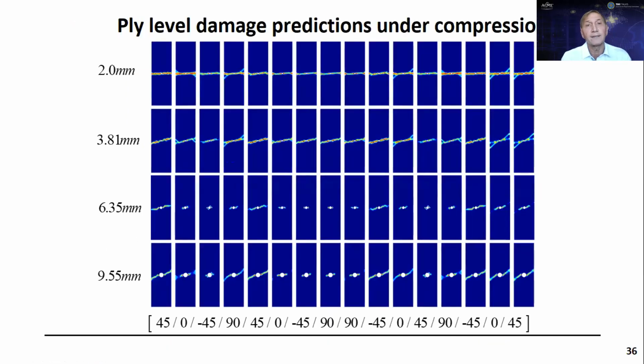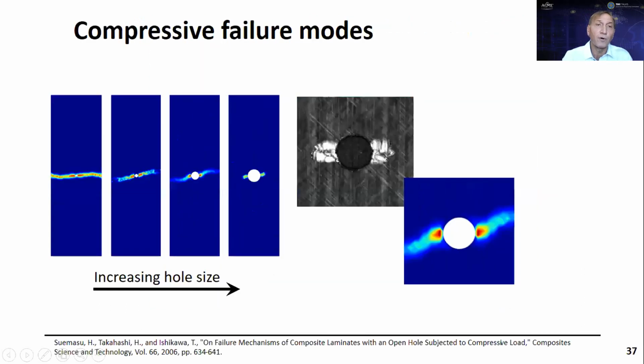And next we'll look at the same laminate, this time in compression. Now, if you remember, for the smaller hole size, we had these slanted failure paths, but now it's very straight, perpendicular to the direction of the applied load, whereas for the larger hole size, you have the slanted damage paths. And if I superimpose them all, as you can see here, as the hole size increases, it very nicely captures what is observed also experimentally.